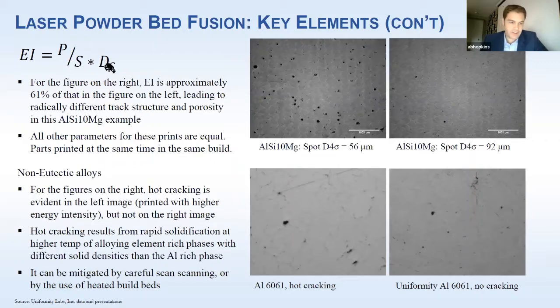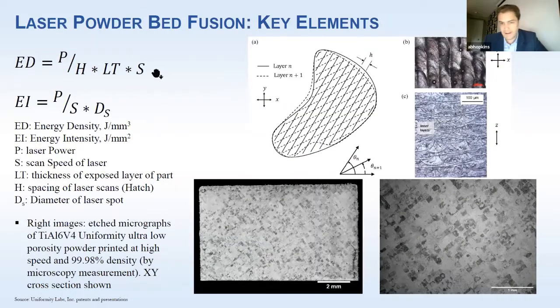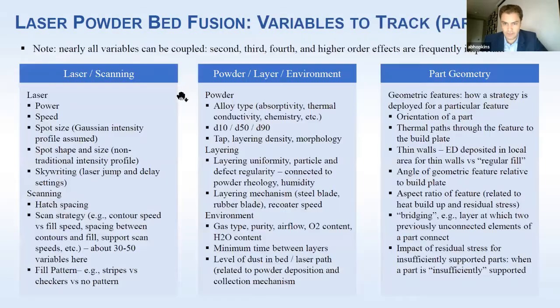Energy intensity, I've given just an example of why it's important. Energy density is for most alloys the most important parameter. And I'll focus on one thing, that if you have denser powders on the bed, for example, I mentioned this earlier, then the energy densities you can print at, for example, for 316L, you can go into the 26, 28 joules per cubic millimeter range, which there's a whole mountain of commercial papers out there saying that's impossible. You have lack of fusion everywhere. You have defects everywhere. What do I mean by that?